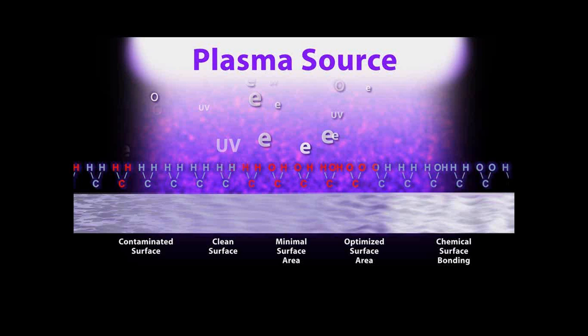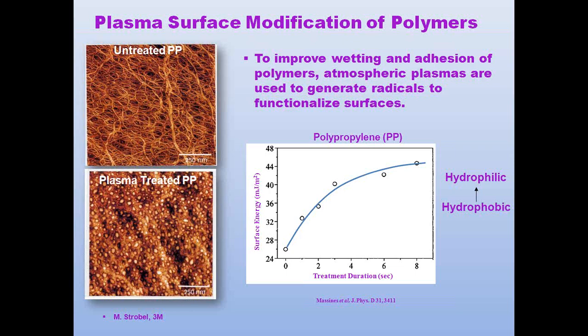When we look at specific polymers, and again, we're going to use polypropylene as the example here, the objective is to increase surface energy relative to time. With atmospheric systems, the time spent is fractions of a second. In this case, we're showing you an example of a vacuum plasma approach, which is a low-density discharge, moving a polypropylene surface from a hydrophobic surface characterization to a hydrophilic characterization. But you can see that the duration time is usually in a large amount of seconds to get up to a minimum amount of surface energy. Again, with an atmospheric plasma, that type of change is within milliseconds relative to the exposure time to these type of discharges. And yet the treatment effects can be the same.